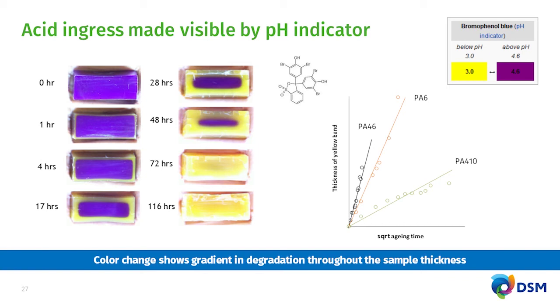But as soon as you put the tensile bar into acidic solutions, you will start to see discoloration. So the yellowing from the skin to the core. So the yellowing really indicates the change of local pH from above 3 to below 3. And in principle, you can actually use the thickness of the yellow layer as an indicator of how fast the acidic species goes into the polymer.